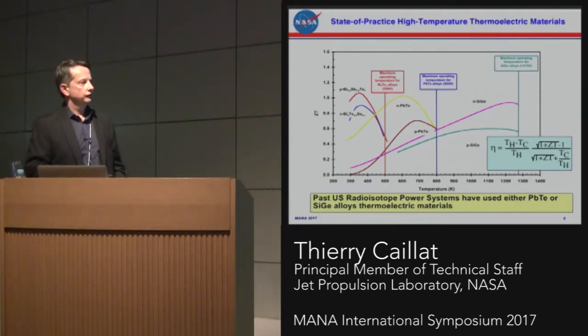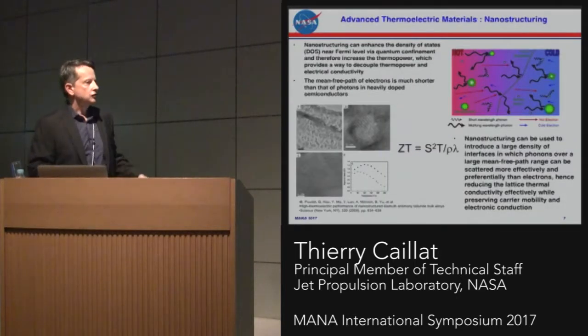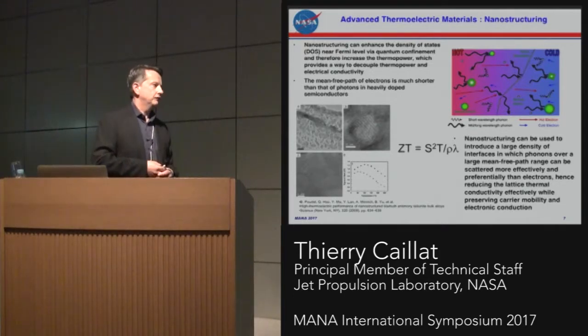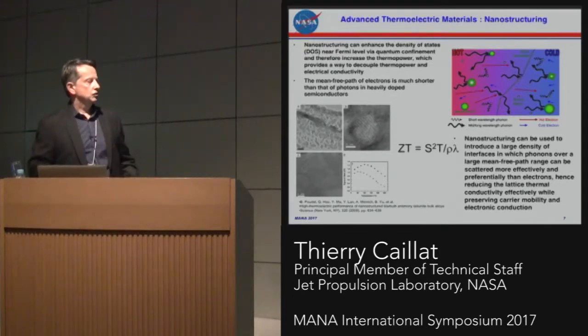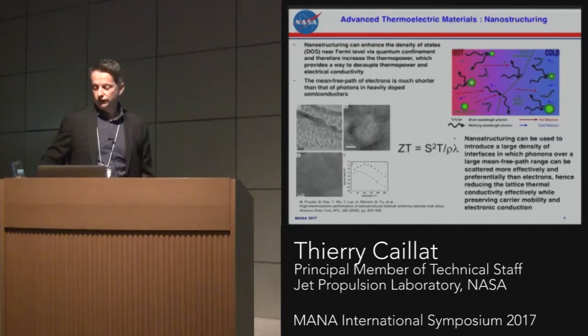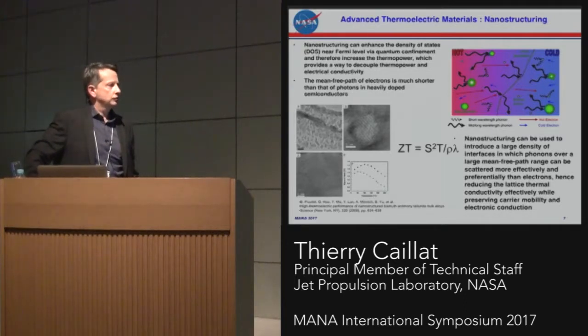I'm going to touch upon the degradation mechanisms associated with those RTGs, and one of them is loss of material by vapor pressure at high temperature, and that somehow limits the highest temperature you can use. So when you're dealing with new advanced thermoelectric materials, nanostructuring has been around for almost 20 years now in terms of the thermoelectric materials.